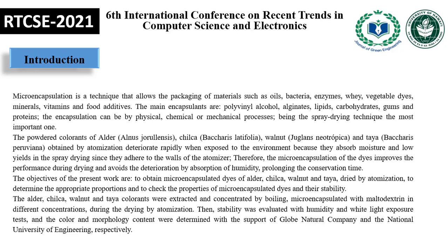The powdered colorants of alder, chilca, walnut, and taya obtained by atomization deteriorate rapidly when exposed to the environment because they absorb moisture, and they give low yields in the spray drying, since they adhere to the walls of the atomizer. Therefore, the microencapsulation of the dyes improves the performance during drying and avoids the deterioration by absorption of humidity, prolonging the conservation time.